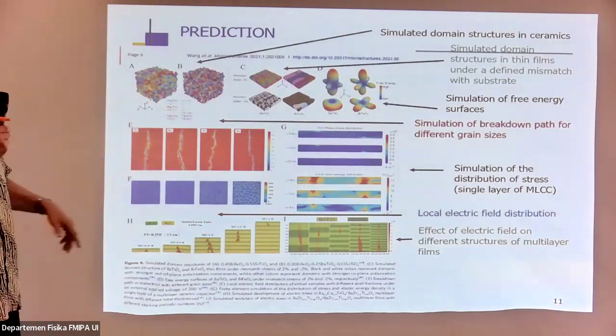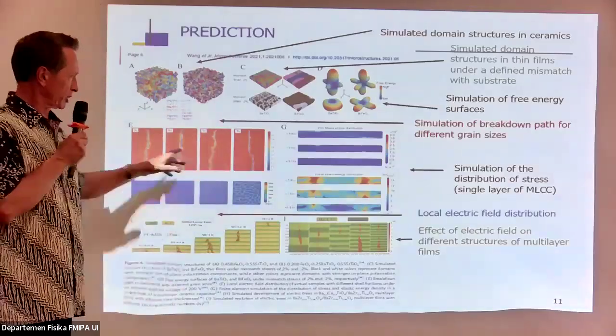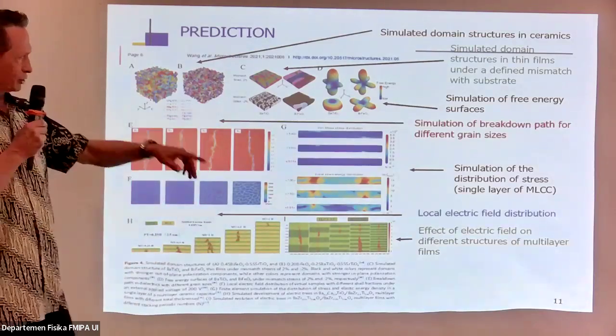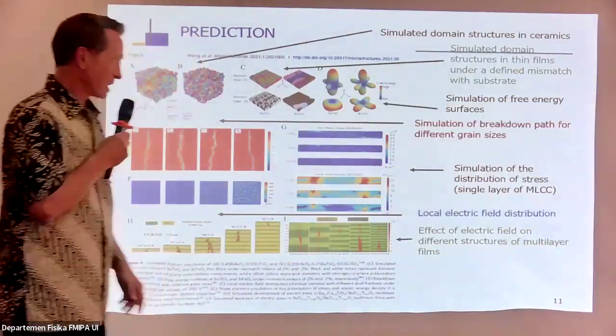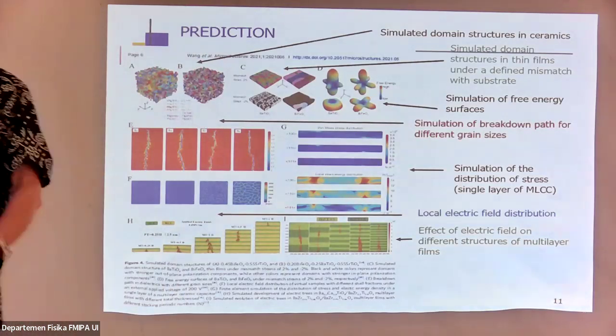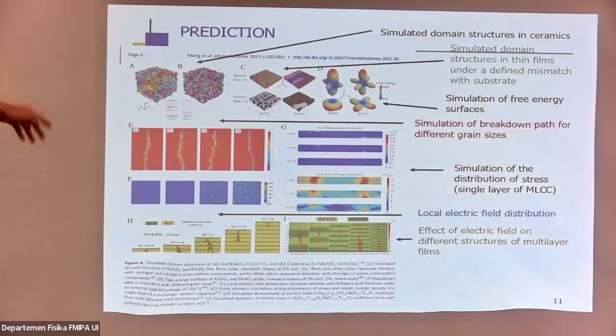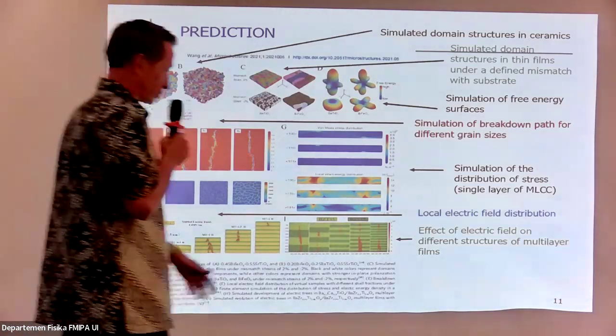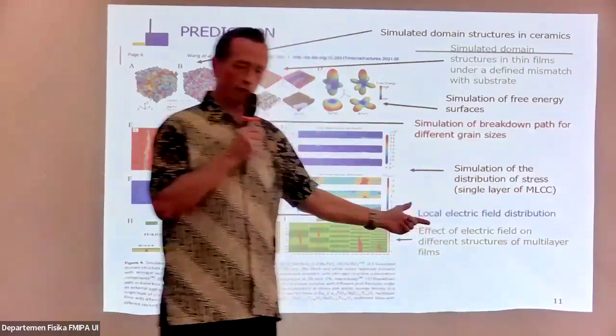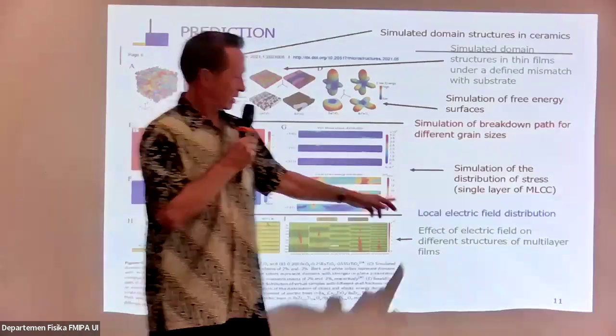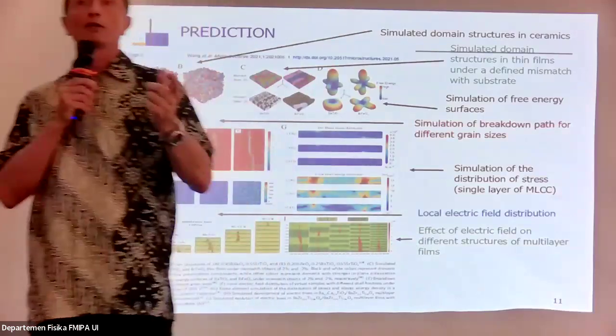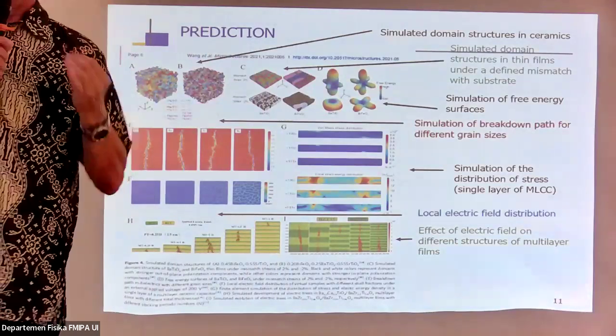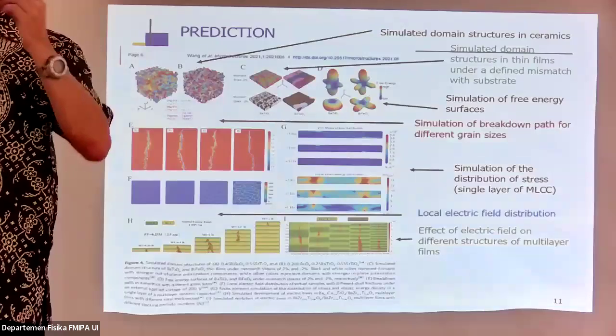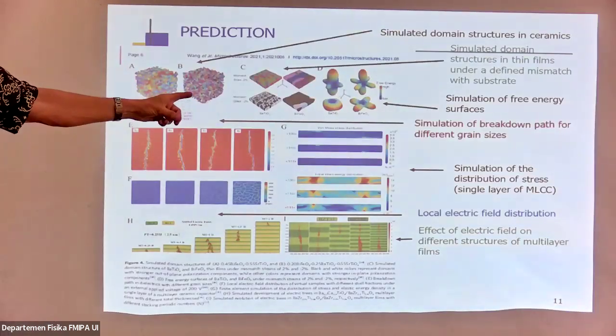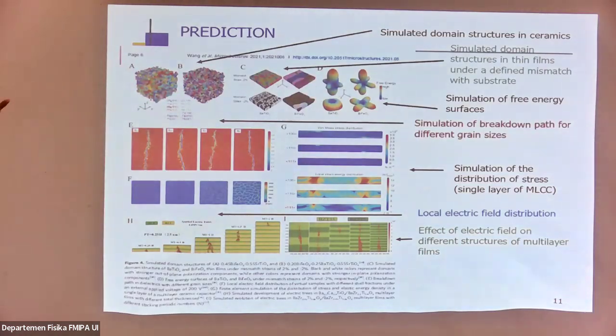So that's why computation can be done to study the effect of the structure or composition on resisting this breakdown. After that, you can also have some simulation for the distribution of stress. Stress is also very important for different kinds of applications, like thermoelastic or piezoelectric applications. Then, this is especially interesting for multilayer structures. You can study the electric field distribution, because if you have a multilayer structure, as a function of the resistivity of each material, you will have a special distribution of the electric field. That's why it's very important to simulate this kind of effect.